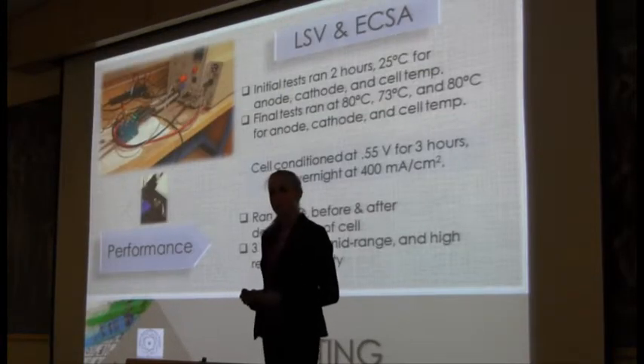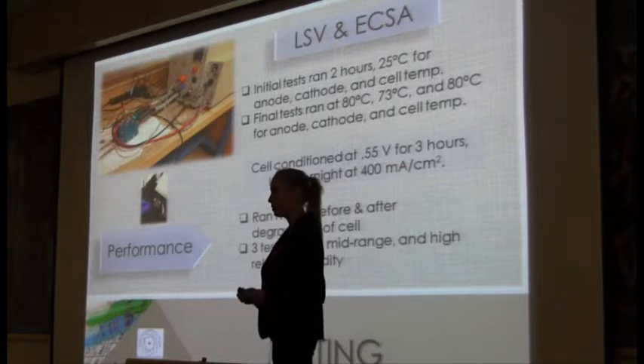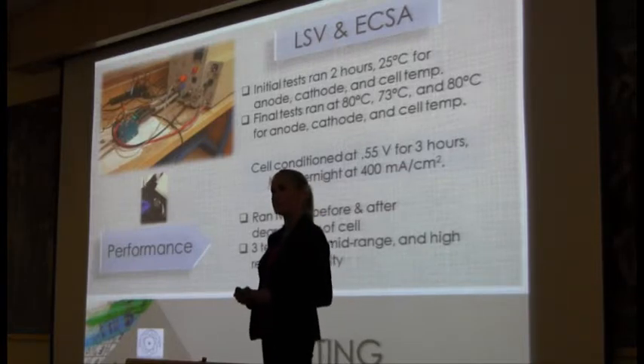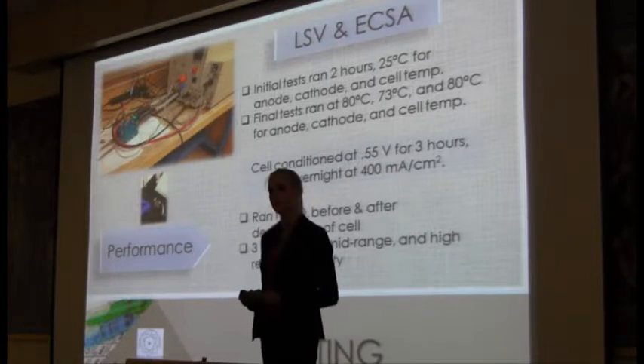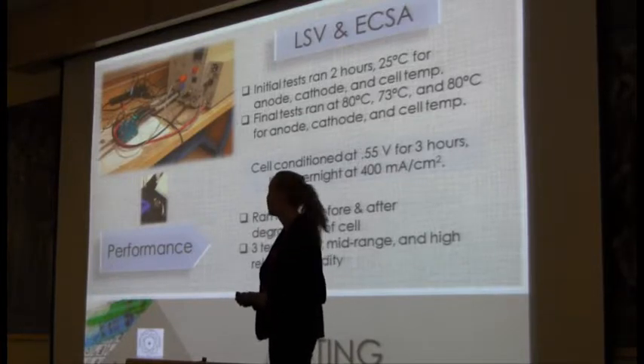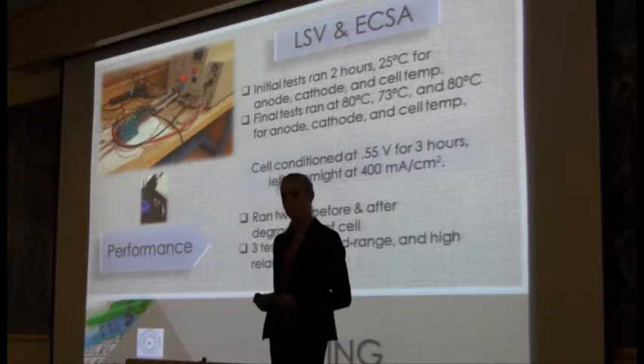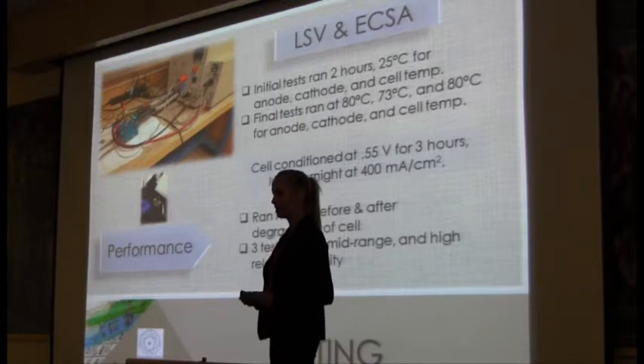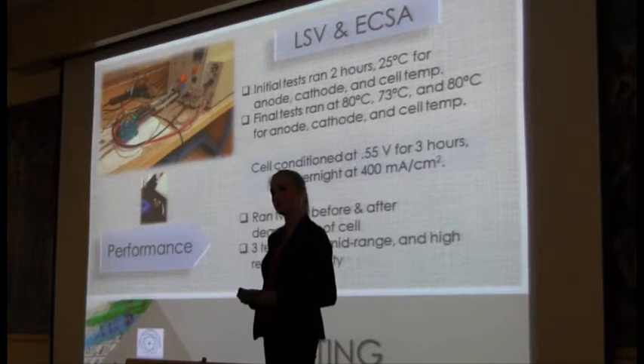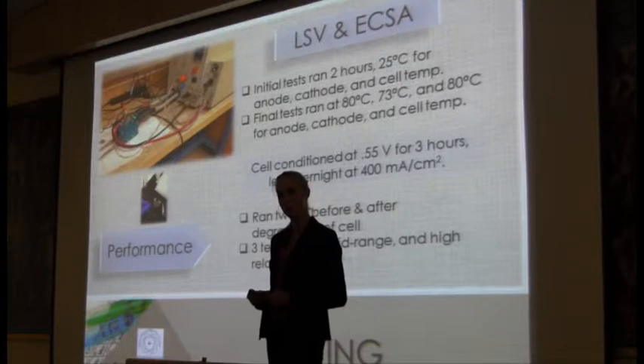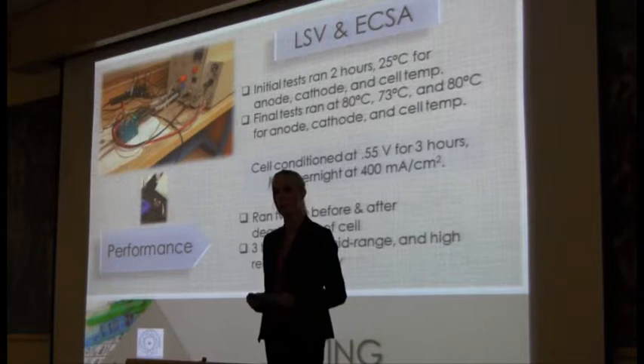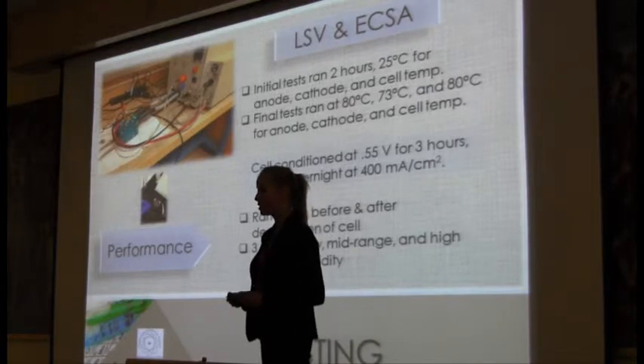We did 3 different tests on the fuel cell. The first test was a linear sweep voltammetry test, or an LSV test, and that measured the amount of hydrogen permeation through the fuel cell and also signaled whether an electrical short occurred in the fuel cell. The second test we ran was an ECSA, or an electrochemical catalytic surface area test, and that showed us the amount of active catalytic surface area on the membrane. The final test we ran was a performance test in which we changed the current and saw what kind of potential or voltage we could get out of the fuel cell. It was run at 3 different types of humidity, 1 low, 1 mid-range, and 1 high, to see how the amount of water vapor in the cell affected performance.